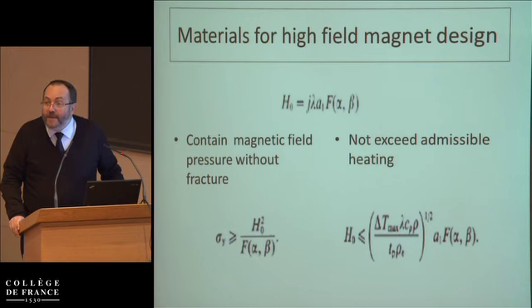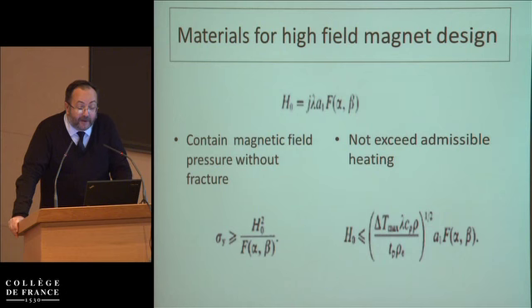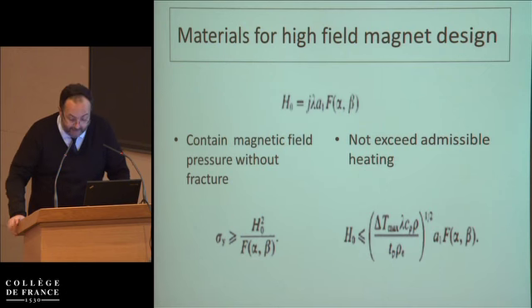They are enormous, which means that you are confining a magnetic field inside a finite space, and this confinement in the finite space gives you a high magnetic pressure. And this high magnetic pressure is really a force on the winding, which might destroy the winding. Now, you need to contain the magnetic field without fracture. That gives you a first criterion between the yield stress and the field that you want to obtain. And of course, you don't want to heat too much, and that requires a high conductivity material, and gives you another maximum field you can reach, which is related to the thermal conductivity, to the diffusivity, and to the electric conductivity of the material. These two combinations of properties are performance indices, which will tell you if the material is suitable to make a high field magnet.